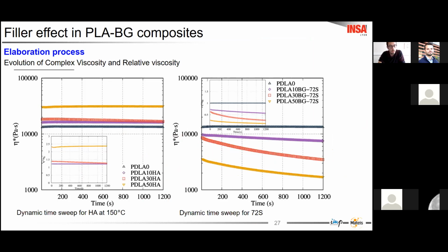On the other hand, hydroxyapatite and bioglass 72S show a better response to time and high temperature. In the case of hydroxyapatite, the viscosity increases as the content of filler increases, and the viscosity remains stable during the whole study. Not the case for 72S, which decreases, but much less than in the case of 45S.